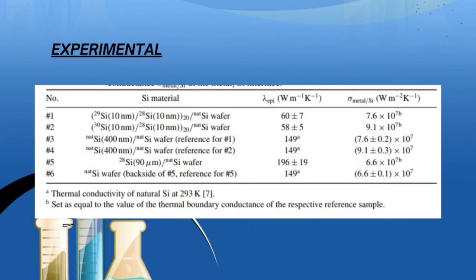Since the preparation of Si isotope structures with different layer thickness, layer sequence and layer numbers by means of MBE and their subsequent analysis with TRXS is far too laborious and time-consuming, we perform molecular dynamics (MD) calculations to determine the impact of various kinds of isotopically modulated silicon layers on thermal conductivity.